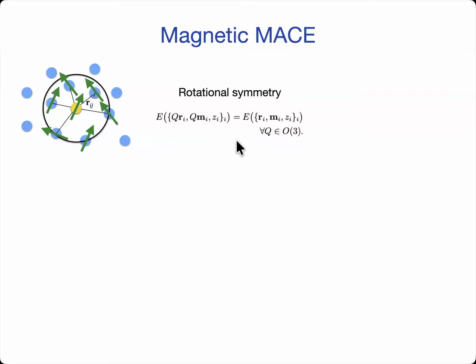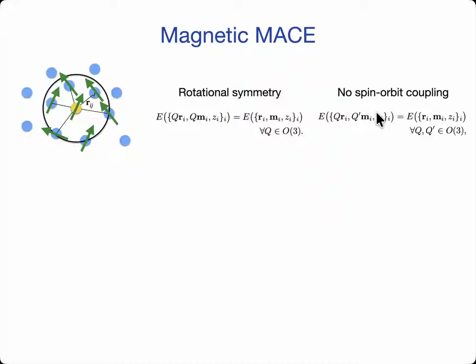You have to be careful about the rotational symmetry because now if you apply a rotation Q to the entire system, you want to recover the invariance of the total energy with respect to a global rotation that rotates the geometry and the spin. If you have no spin-orbit coupling, then you can rotate the spins and the positions separately. So you rotate the positions with Q, the spins with Q prime, and you should still get the same energy. But if you have spin-orbit coupling, then this larger symmetry doesn't apply. So this is not too hard to implement.